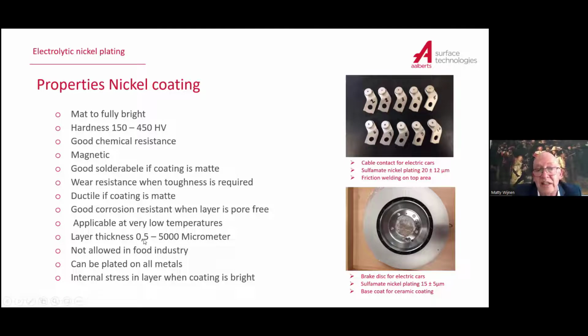It has layer thickness from, say, 0.5 micron to 5,000 micrometers. It's not allowed in the food industry, and we can put it on every metal. When you put it as a matte nickel, it has very low internal stress. When you have fully bright nickel, it has a lot of high stress. On the right side, you also see brake discs, which we did for electric cars, where we put nickel under the thermal spray coat, ceramic spray coat, which is still running at our site in Deurne at this moment.